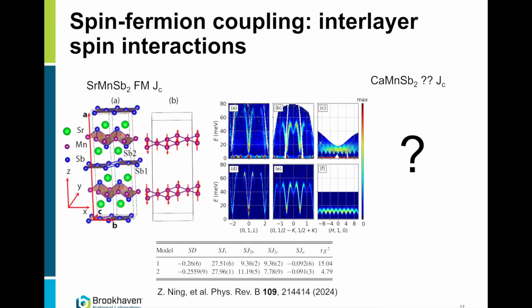Okay, so we set up to measure a similar compositional dependence in the antimonide series, but our samples were too small. I mean, usually, if you want to do compositional work, you don't have big samples that neutron scattering spectroscopic measurements require. So traditionally, a spectroscopic measurement requires gram plus samples. Cheddar made us like 100, 200 milligrams at best samples with different compositions of calcium, strontium, manganese, antimony 2. And so we were stuck. So the end material has been measured by Ames group. They have refined the interlayer coupling to be ferromagnetic. But our work was stuck here.